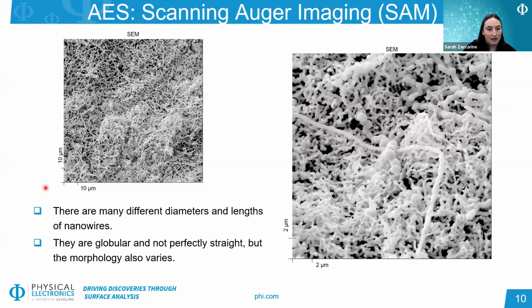So we started by looking at some large field of view images of these nanowires, and we noticed a few things right away. We can see, even zoomed out, that there are a lot of different types of wires present. And if we zoom in a little bit, you can see this even more. We have some wires like this one that are very long, so we have differing lengths of the nanowires. We have some different morphology. Generally, they're pretty globular looking, especially this one. There's a couple that are much more globular looking. And there's also a variety of lengths, diameters, and sizes of these wires. So we have a heterogeneous size and morphology distribution of these wires to start with.